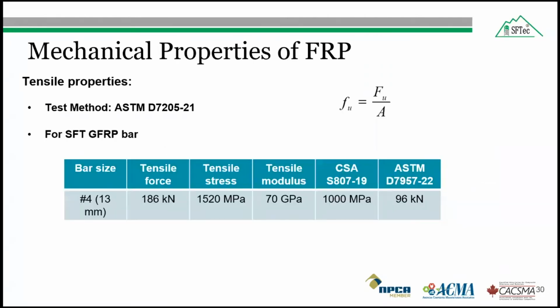And for the SFTec glass fiber reinforced polymer bar number 4, the average tensile force was found to be 186 kilonewton, and this was sufficiently higher than the ASTM D7957 requirement of 96 kilonewton. And also the tensile stress was 1520 megapascal, which was greater than the CSA S807 requirement.